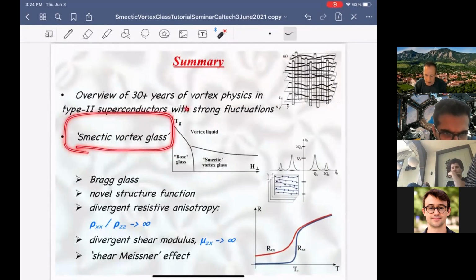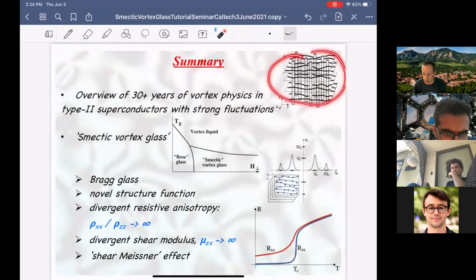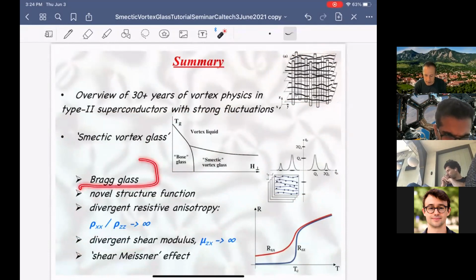I predicted a Smectic vortex glass phase that's illustrated here. Here's the phase diagram as a function of a transverse field. It has an interesting structure that's very anisotropic, that you can detect in scattering, neutron scattering, for example. It has a divergent resistive anisotropy that's schematically illustrated here. It has a divergent elastic response, which I call a shear Meissner effect. And I believe this state is, for weak disorder, a true Bragg glass state. So with that, let me quit, and thank you for your attention.